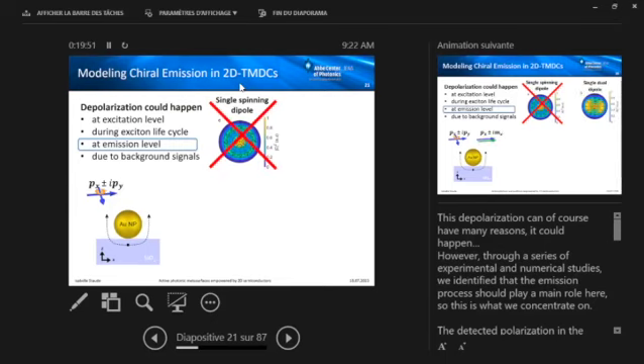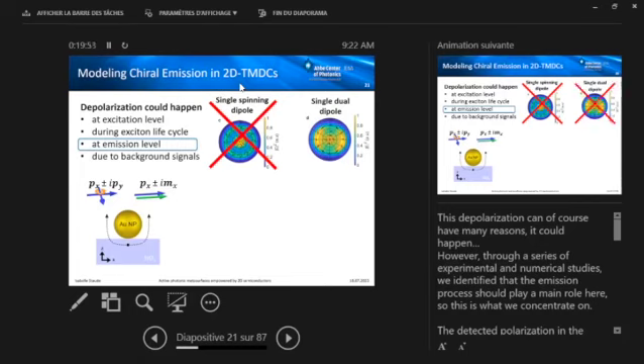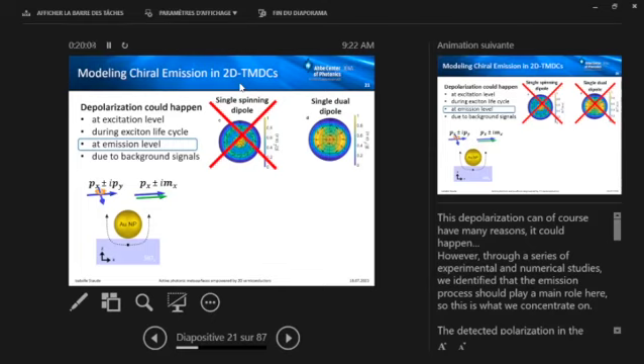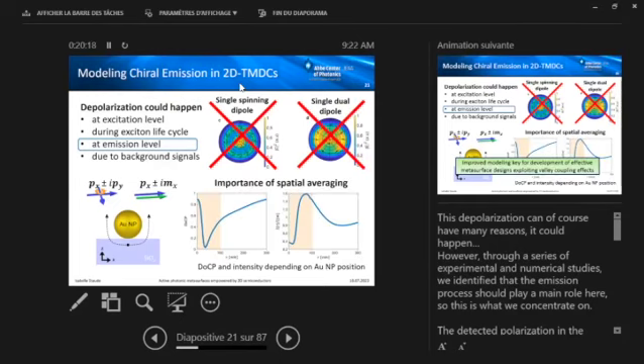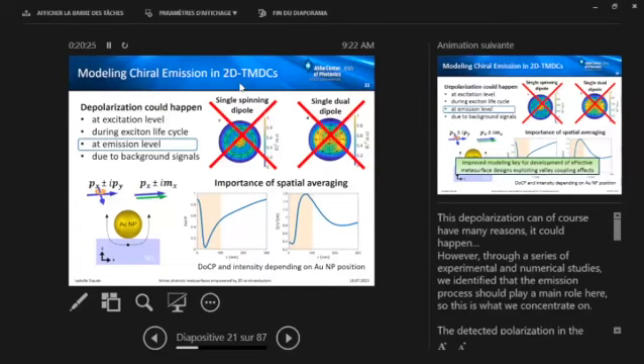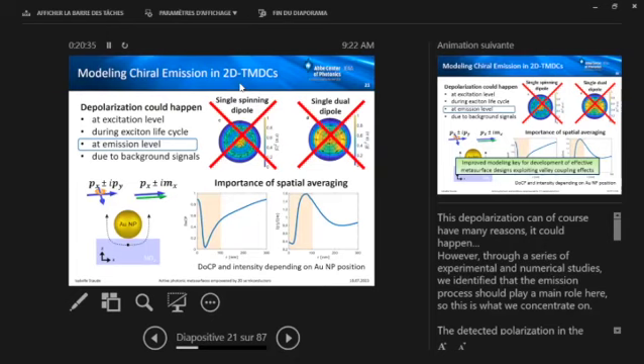So, at some stage, we had the idea to use a different kind of dipole source, which is also chiral, namely the dual symmetric dipole pioneered by Ivan Fernandez-Corbaton from KIT. We also simulated that, and firstly, we were quite excited because it looked like a depolarization, but the thing is that this does not predict the polarization properties of the monolayer away from the nanoparticles. So we also have to discard this. And what we now found is that the whole effect can really be explained by spatial averaging. So, whereas we have this high degree of circular polarization if the dipole is located at the center of the nanoparticle, if we move the two away from each other, this very rapidly decays.